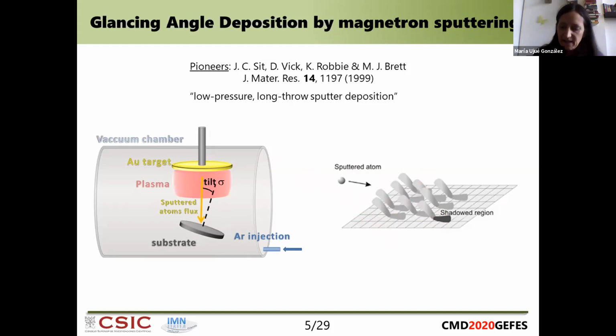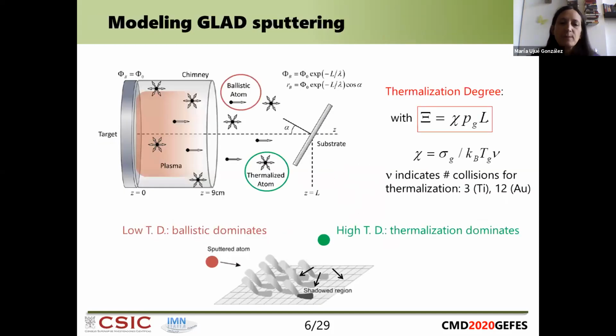Of course, the process is a little bit more complex than that, because we are talking about sputtering, so we have an argon gas for making the plasma in order to extract the atoms from the target, and this is going to make collisions with the atoms that we are trying to deposit, and this is going to change the angles, so we are not going to have such a directional effect to have the shadowing and the nanocolumns. So there is a balance between the pressure of the plasma and how we can deposit this on the substrate, and so we can play with the different conditions here.